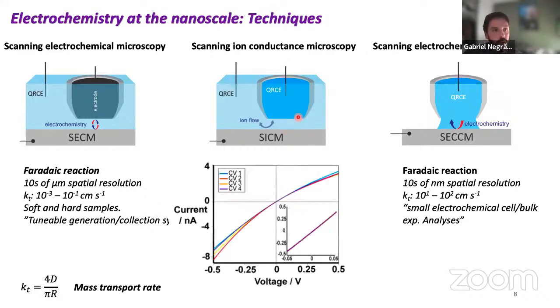I say that's an oddball because if I look at a CV of an SICM, it looks quite different than you guys expect. It's just a line. It's not a straight line. If I look very close to zero potential, it's a straight line, which I expect as a resistor because of a very small pore. But if I go to larger potentials in both directions, you can see there's a distortion from this resistance. And this is showing that there is an asymmetric transport of ions because the double layer of the glass, because it's so small, is changing the ion transport number here, but also the substrate, if this is close to the substrate, also impacts that. So I can start to infer and get information from a substrate double layer just by looking at how this current is deflecting.